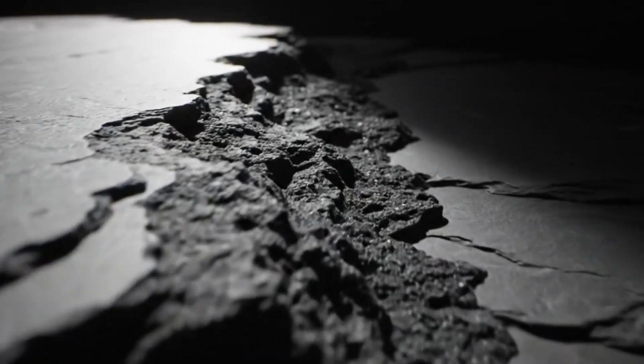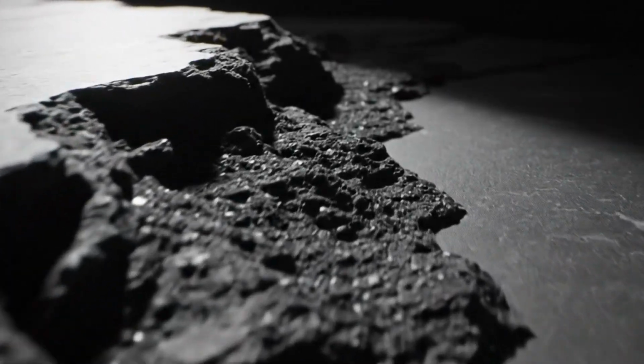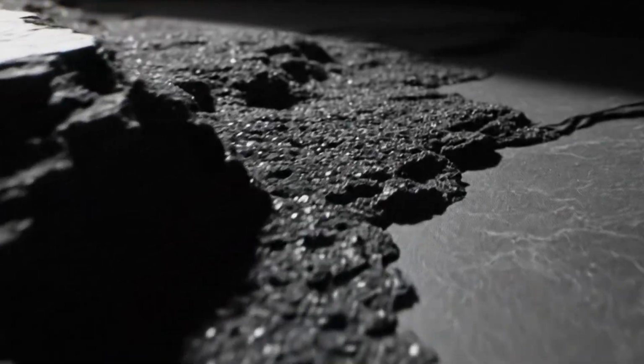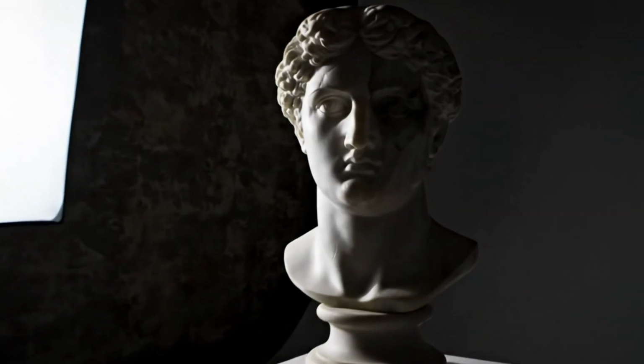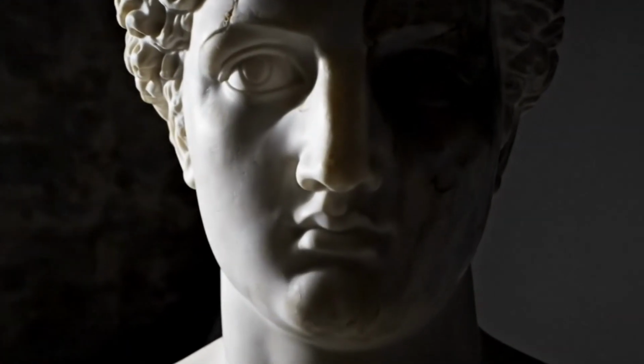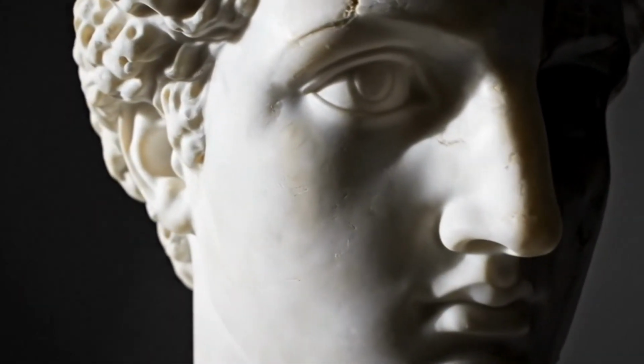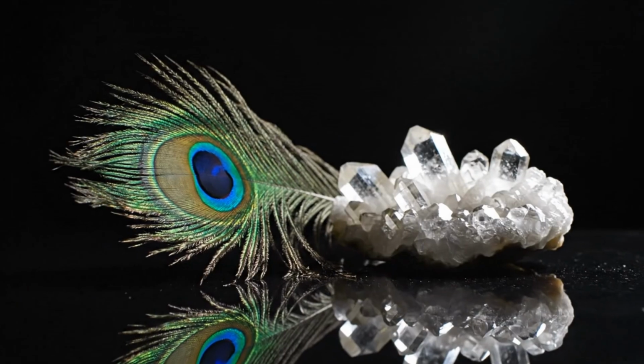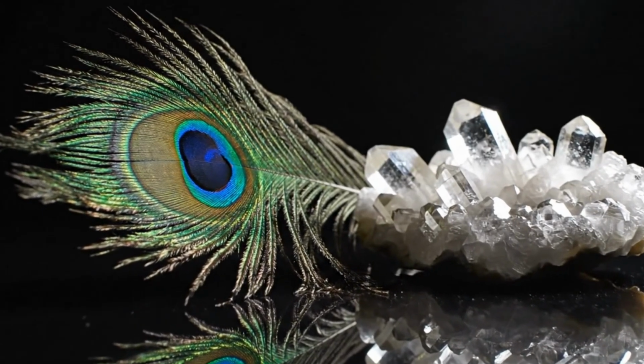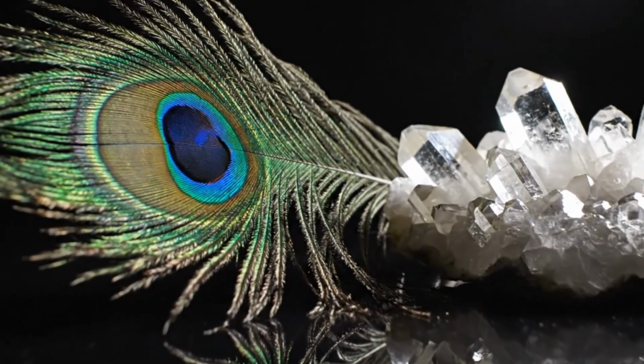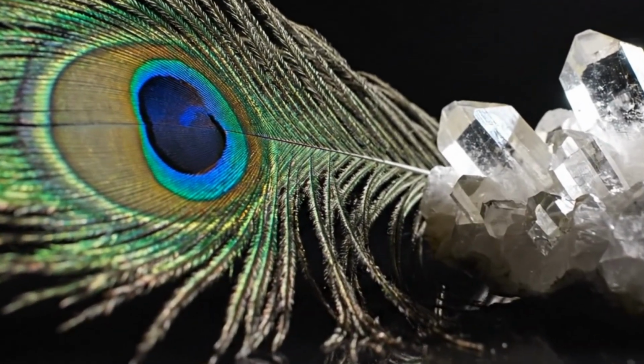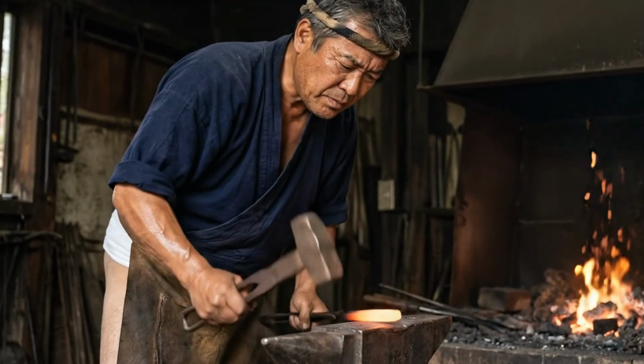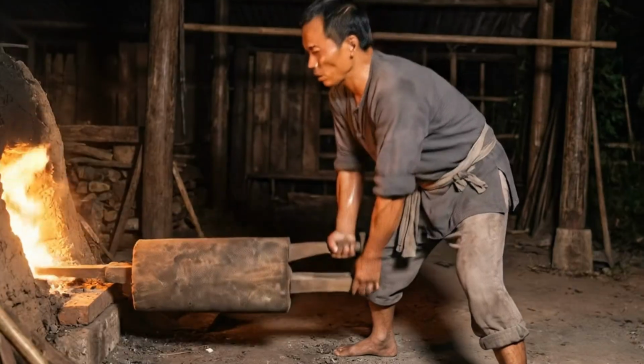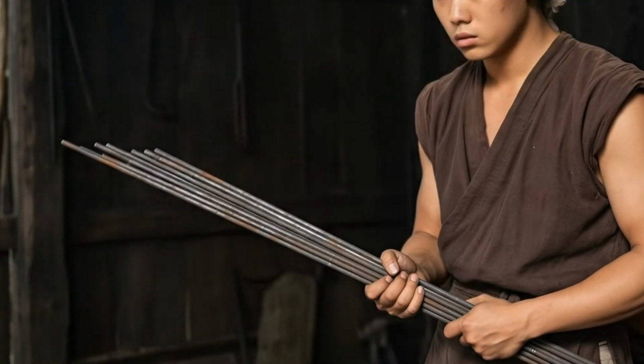The result is a material that behaves according to principles almost identical to those behind modern fiber-reinforced composites, including carbon fiber. When a crack initiates in the blade and attempts to propagate, it encounters these internal boundaries. The crack deflects, divides, and dissipates, rather than running clean through the material. The blade resists fracture not because it is monolithically tough, but because its internal architecture interrupts the failure mechanism at the microscale. This is what material scientists mean when they describe the structure as a natural composite. And it is exactly the quality that disappears when the production process is made too clean.